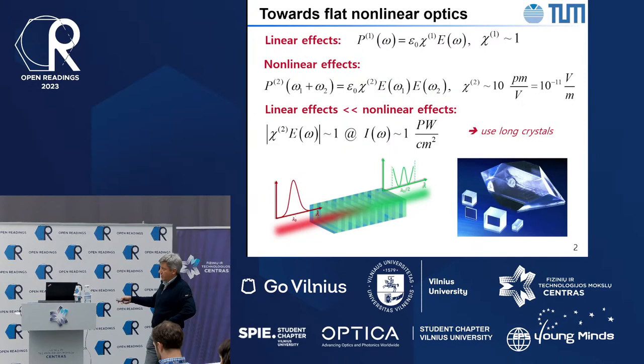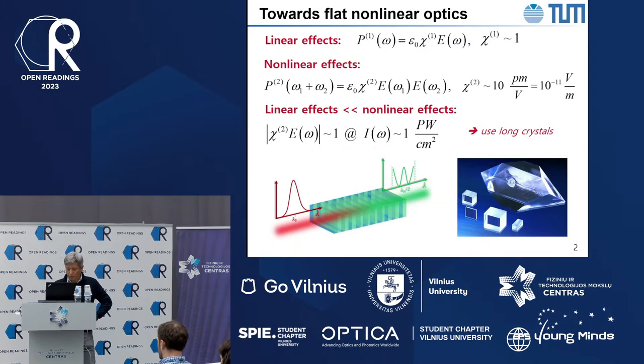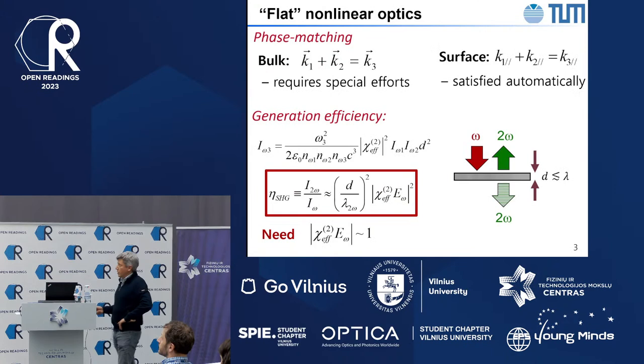And when they are long and span many wavelengths, you need to worry about the concept of so-called phase matching, where each layer of this crystal has to provide the output at, let's say, some frequency in phase with all the other layers. And that puts severe restrictions on the bandwidths at which a single crystal can generate light, and limits you in many ways. So if you manage to convert light in thin sub-wavelength films, you first of all don't need to worry about phase matching.